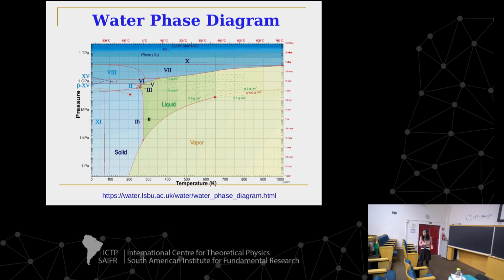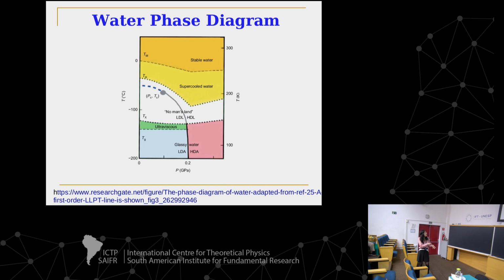I might say in favor of this hypothesis that if you quench very quick, you decrease the temperature very fast, either here or here, you find two amorphous phases. One high density amorphous phase and low density amorphous phase. But this is out of equilibrium type of experiments, and there is no guarantee that they become a low density liquid and a high density liquid. So this is again the same phase diagram in which here this do exist, the low density amorphous phase and high density amorphous phase, out of equilibrium, the system becomes super viscous.